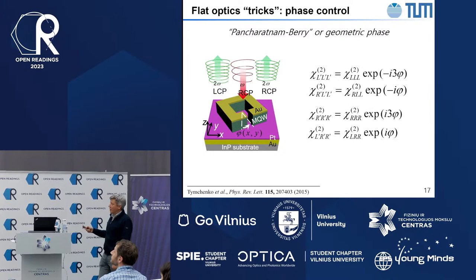It's called geometric phase. If you send circularly polarized light and you have an antenna, it will also generate circularly polarized light in the output. The rotation of the antenna amounts to a phase shift in the response. Now, it's easy to understand conceptually. Basically, if you think about this antenna and you think about the input light, which is circularly polarized, at any given moment in time, the electric field of the circularly polarized light is in a particular direction. And that particular direction of the electric field corresponds to a particular distribution of currents in that antenna.